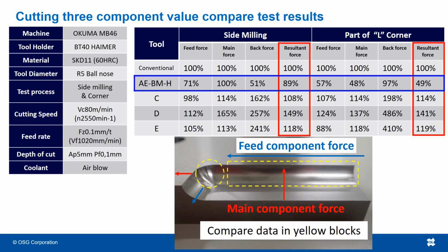Here are some cutting test results comparing the AEBMH and its resultant force, in both side milling and part of the corner, compared to other conventional mills. This was done in SKD11 material at 60 HRC, which is roughly the equivalent of D2 tool steel. As you can see, thanks to the unequal spacing on the end cut, as well as the increased spiral curve, you can see that the AEBMH had lower overall resultant forces compared to the other conventional mills.